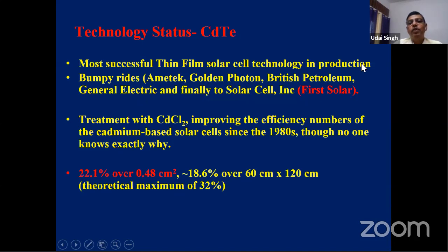So these many companies started on cadmium telluride. They have all closed. Only First Solar is surviving, and they have manufacturing plants in the US and in Malaysia. One of the advantages: people found that if they treat the cadmium telluride with cadmium chloride, that improves the efficiency, because it's basically a flux agent. It promotes grain growth, so that is a breakthrough in this technology. Now 22.1% on around 0.48 centimeter square is the highest efficiency achieved. Module wise, they are around 17 to 18%, but in regular production they may be around 14 to 15%.